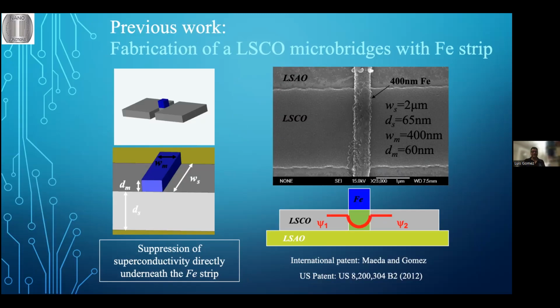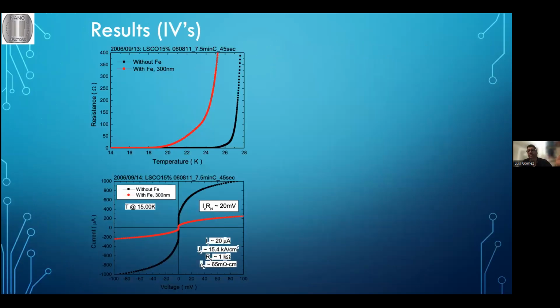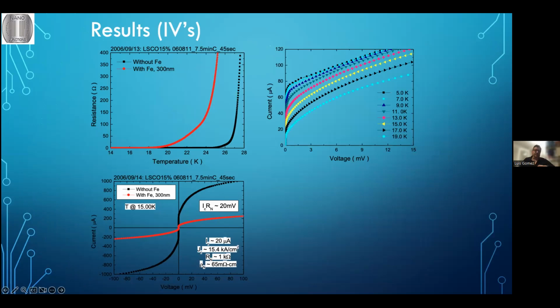So the next step will be to just characterize these samples. Again, this is the same resistance versus temperature curves. We do an IV, but now we vary the temperature everywhere. So we start from the lowest temperature, 5 kelvins. It doesn't show on this scale. So this is 14 kelvins, and 5 kelvins will be somewhere around here, so from 5 kelvins to 19 kelvins, which is around here.